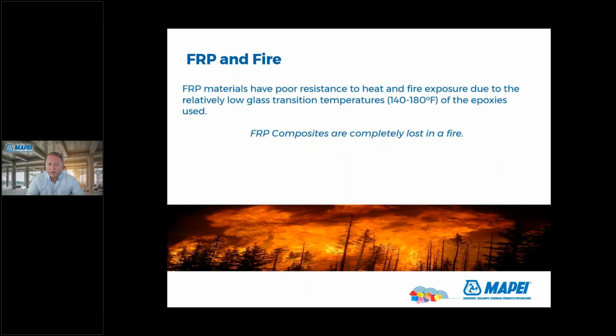So in regards to FRP and fire, FRP has a poor resistance to heat and fire exposure. Typically around 140 to 180 degrees, the epoxy just begins to transition from a cured state to a softer state. They call it the glass transition temperature. ACI says FRP composite should be considered completely lost in a fire event. Think of a 1,000-degree hydrocarbon fire.